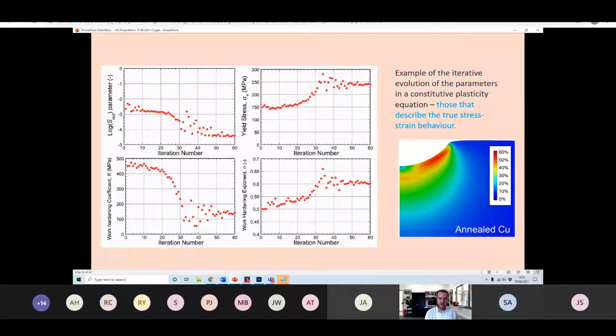Now, let's see what that looks like in reality. What these plots show is the iterative evolution of those free parameters in a constitutive plasticity law that begin to converge after about 50 iterations. What's also shown in the top left is a parameter called S-red, which is the parameter describing the goodness of fit between measured and predicted profile shapes, and it too converges after about 50 iterations, and that forms the basis for the analysis being stopped.